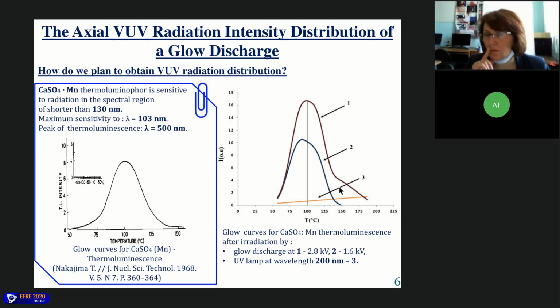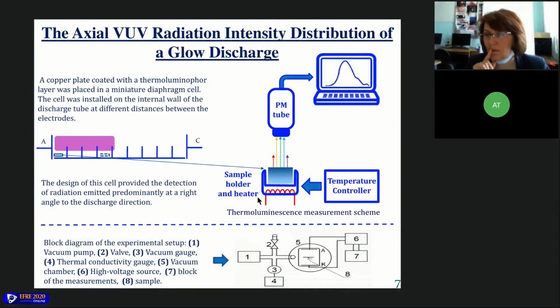Next slide, slide number 7. To obtain the axial vacuum ultraviolet radiation intensity distribution, a special copper plate coated with this material layer was placed in a special diaphragm cell, you can see here. The cell was installed on the inside of the discharge. You can see a block diagram of the experimental setup here. After irradiation, the sample was heated and its thermoluminescence curve was obtained by this scheme.